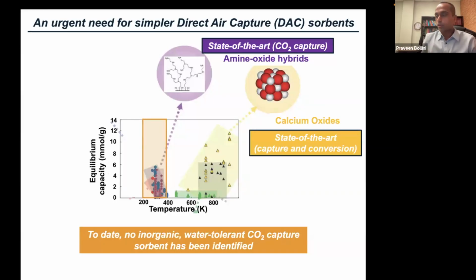Now, the point I'm trying to emphasize here, and what I'll describe briefly in the next few slides, is that you can in fact use inorganics, like the one you see in the top right, to do direct air capture at room temperature, and in fact at low temperatures below 100 degrees Celsius. And that's really the discovery that is a new direction in the field of CO2 capture, we think, because you're able to match somewhat the cost profile of a calcium oxide or a magnesium oxide with the performance of a supported amine sorbent, which has an organic and hence tends to degrade.